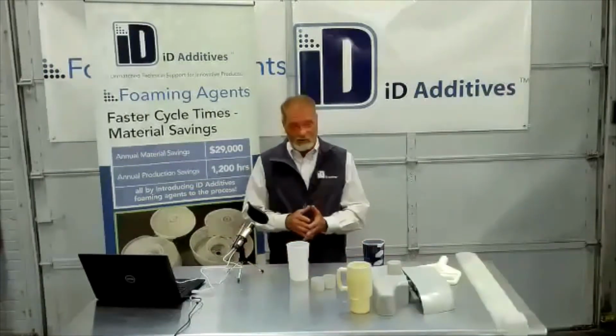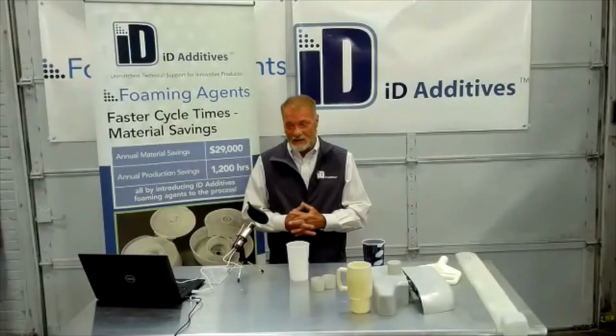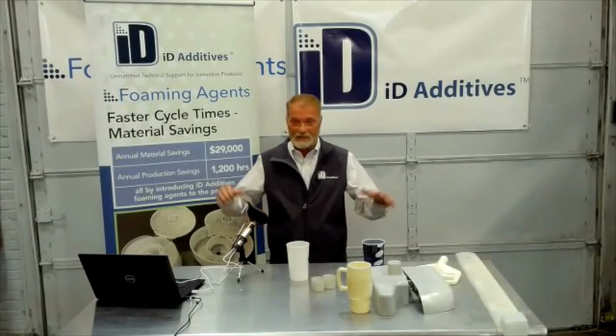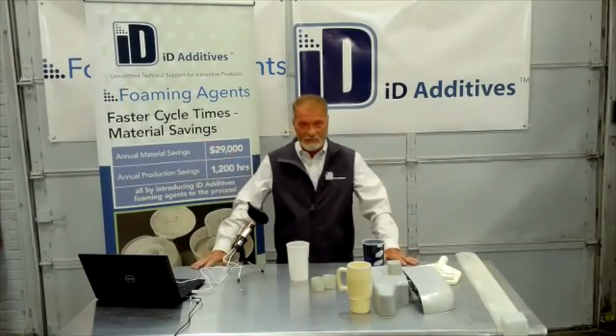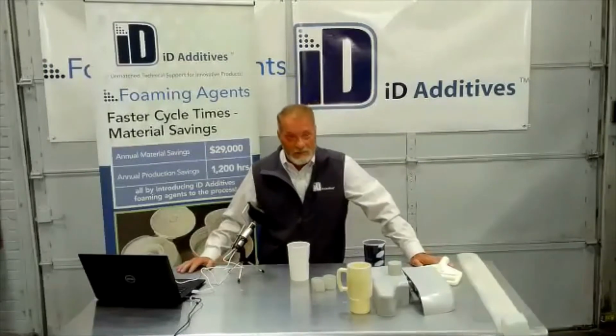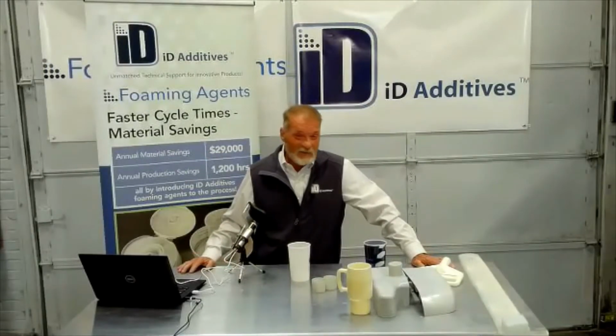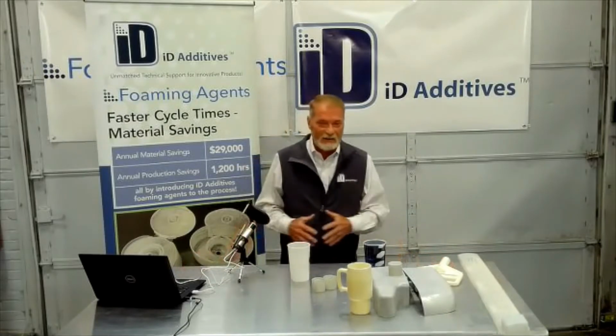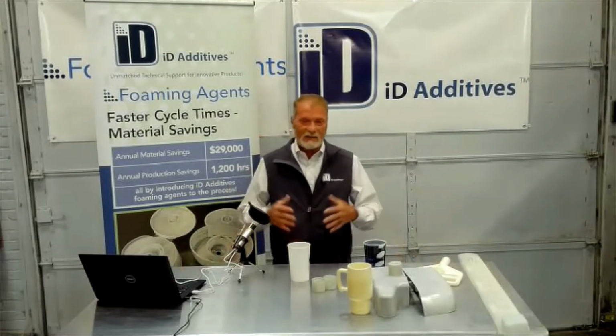I did an extruder test out in Atlanta. They were running 480 top temperature down to 420 in the rear. I mean, it was like pulling teeth to get them to drop those temperatures. But today, they're running 385 in the front and 320 in the rear. And it's foaming like crazy. So the viscosity change is very evident. So take advantage of that.